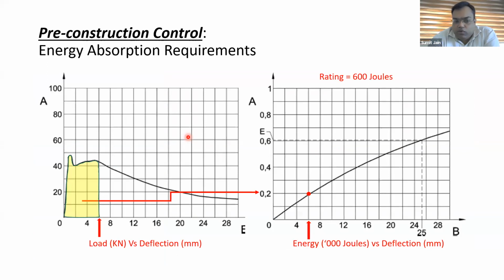For example, if we talk about 6 mm deflection, then the area under the graph shown in the yellow portion is the cumulative energy absorbed up to 6 mm deflection, and that is shown by a red dot on the right hand side of the other curve. So at the same deflection, we have a 200 joule absorption up to 6 mm deflection. When we are doing the test, both these curves are getting plotted in the apparatus.